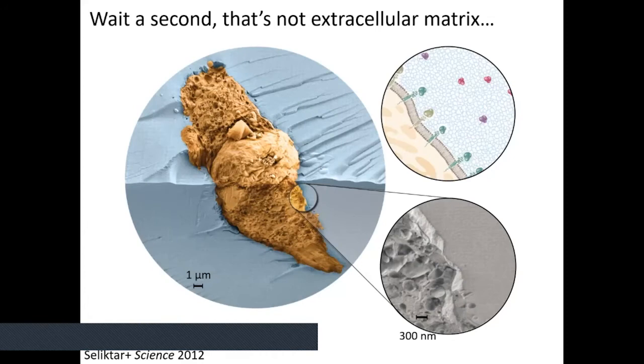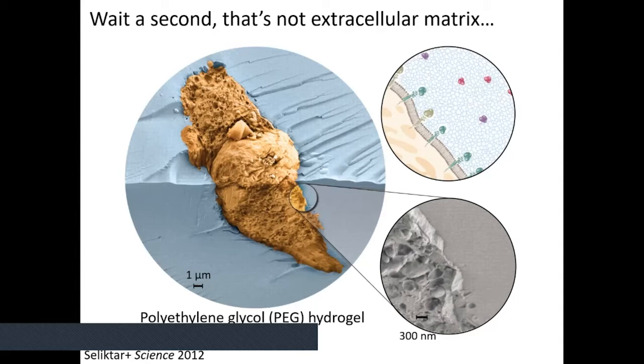Why is this the case? This SEM — actually not a cracked sidewalk but a cell embedded inside a polyethylene glycol hydrogel — shows that relative to the scale of a cell, the pores are tiny, nanoscale. This is quite distinct from the open porous networks of fibers that cells inhabit in natural tissues. Because these are individual polymer backbones that are angstroms wide and cross-linked together, you get this nanoscale porosity that has no similarity to the natural tissue spaces in our body.